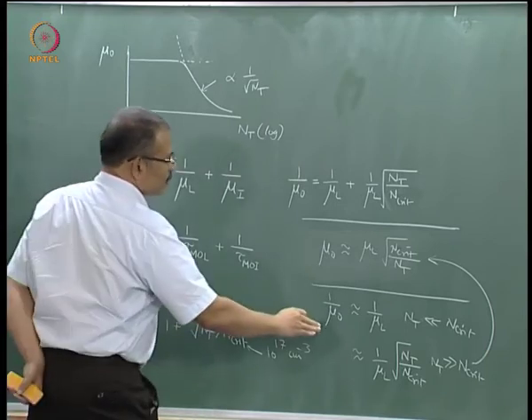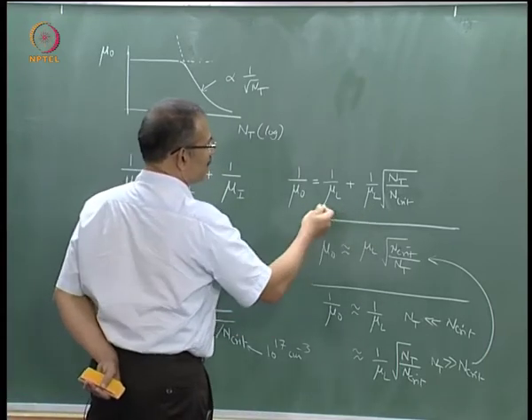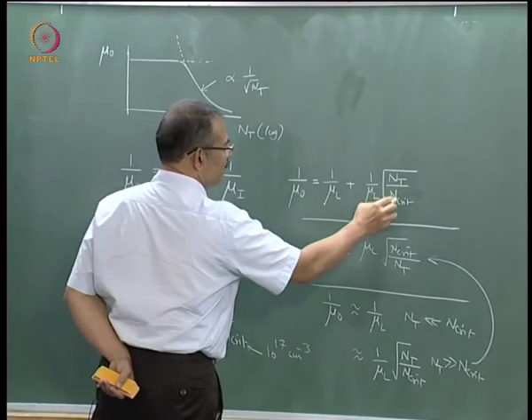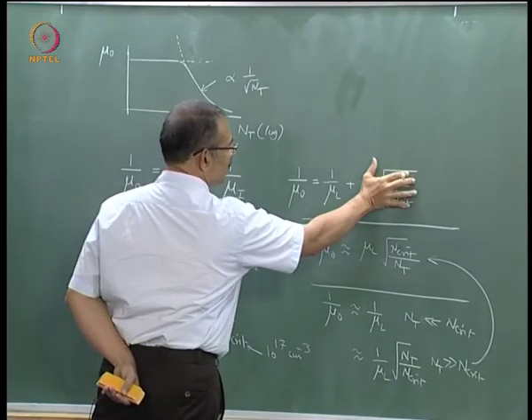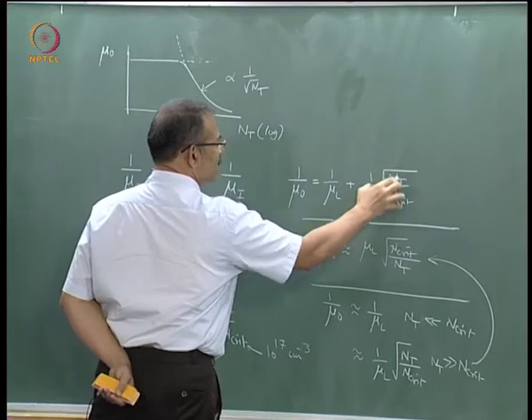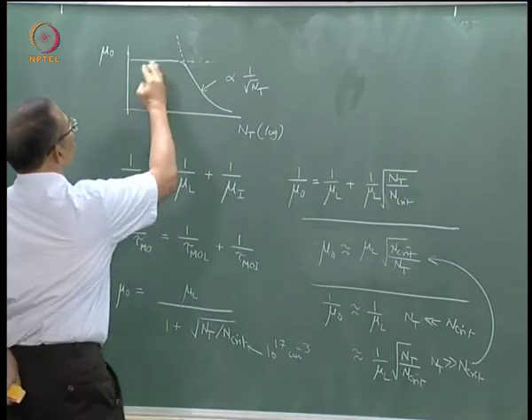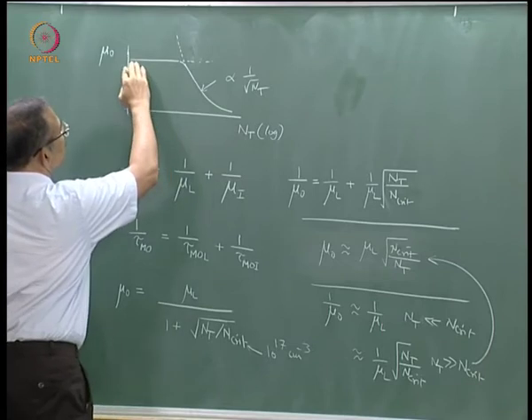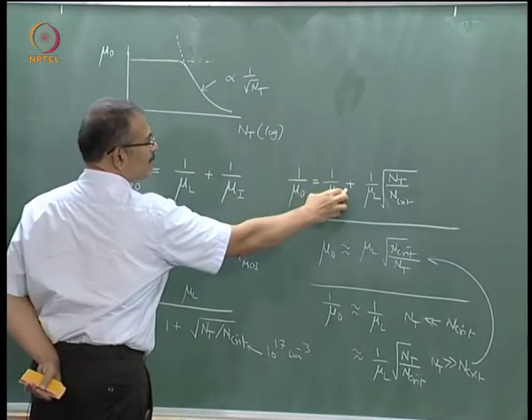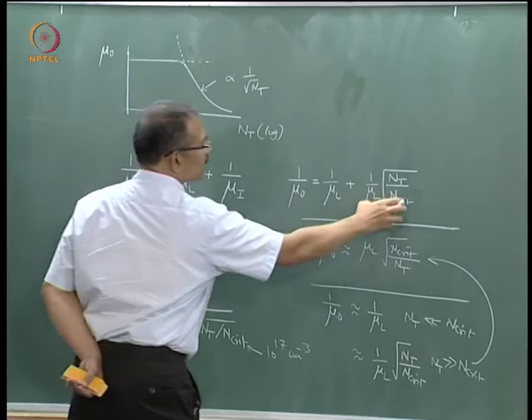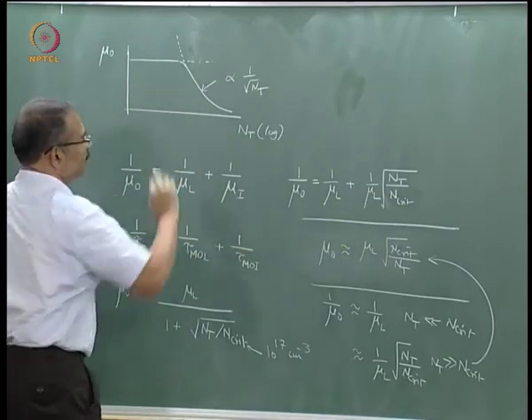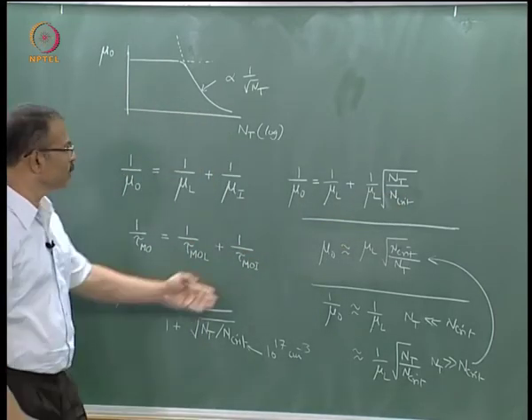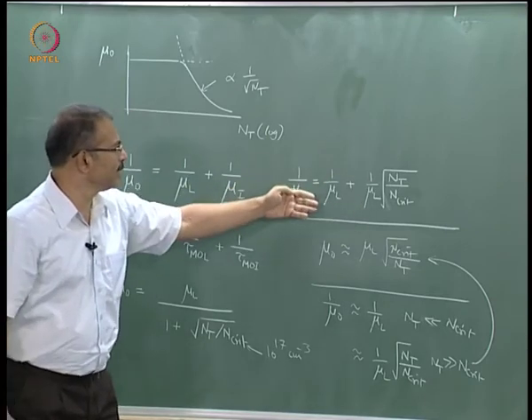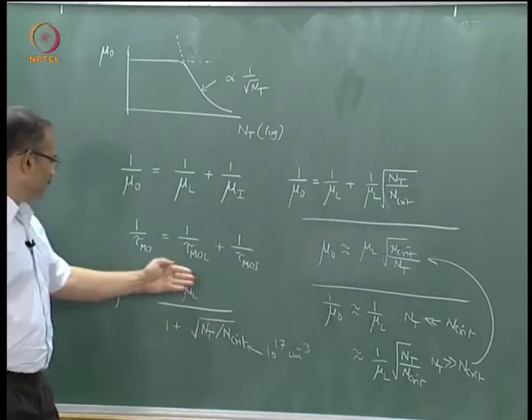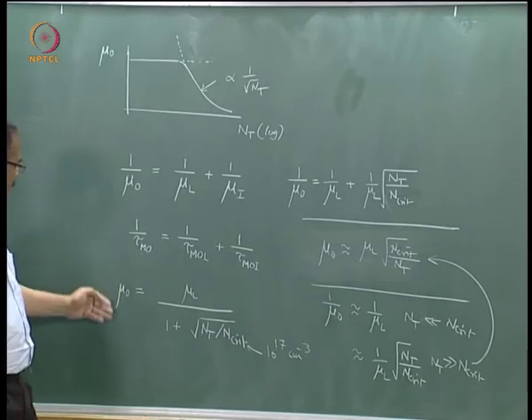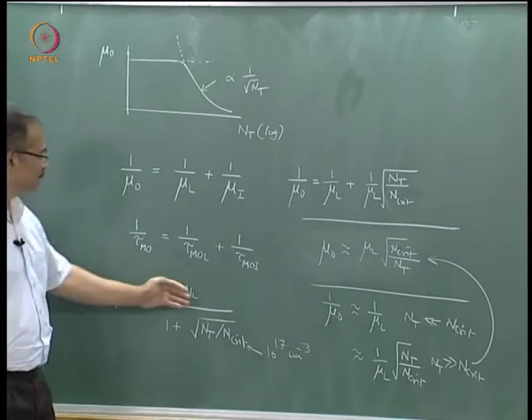Now because of the way we are adding up, because it is reciprocal, when nt is small, this quantity does not hold. When nt is large, it is this quantity rather than this quantity. That is how your curve is asymptotic to this limit for low nt and to this limit for high nt. That is how you get this shape, and that is how you get this formula. When you transform this formula, which is written in the reciprocal form, to the form where you directly want an expression for mu naught instead of 1 by mu naught, then you get this.